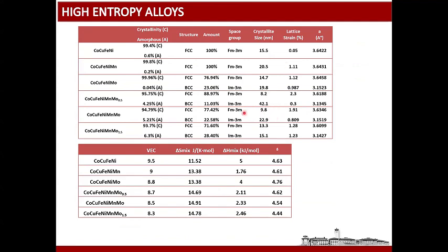So these are obtained from the Rietveld analysis of the X-ray diffraction patterns, and this is in accordance with the expected crystal structure from the theoretical calculations as well. So the valence electron concentration decreased to 8, which is for the mixture of the FCC and the BCC structure. And then the entropy of mixing increased and delta decreased as well. Decreasing delta means increased stability.